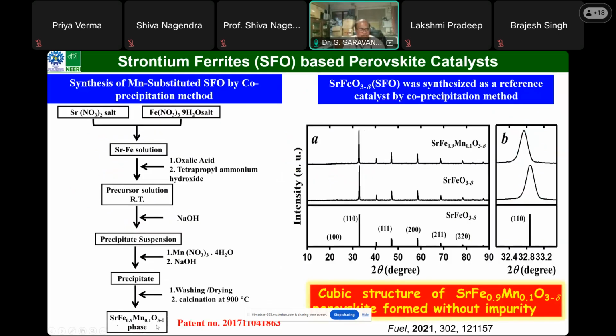So we have prepared manganese substituted strontium ferrite, and when we tuned the various compositions, beyond 20% of manganese the phase is not stable, and we found that 10% substitution of manganese showed better performance. So I have shown this one here.